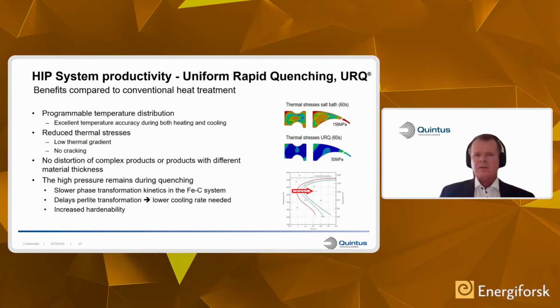What we've seen is that we will have an even temperature distribution, and the temperature accuracy, both in heating up and cooling down, are excellent. And we are able to reduce the thermal stresses, which could lead to cracking. And we talked a little bit about distortions also, and with the Quintus press, we see no distortions on complex products or products with different material thicknesses.